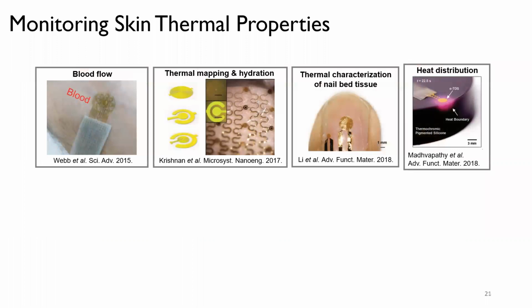You could imagine then, of course, using this in a wide range of different applications. One example would be measuring blood flow. You can actually measure the velocity of blood flow by using an array of sensors around a near-surface vein. If you're sensing with one and running current through another, and let the other ones just read the resistance, you can actually calculate blood velocity. Then we could integrate this with impedance sensors. So we have a regular resistor, and then we have impedance, and you're looking at hydration and thermal mapping at the same time over an array of space.